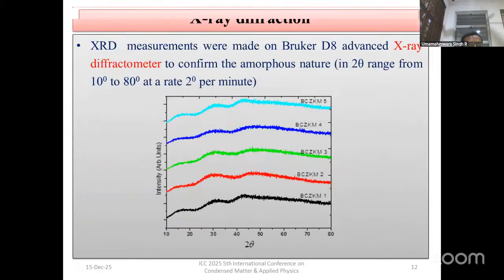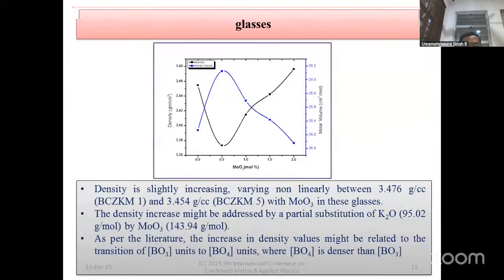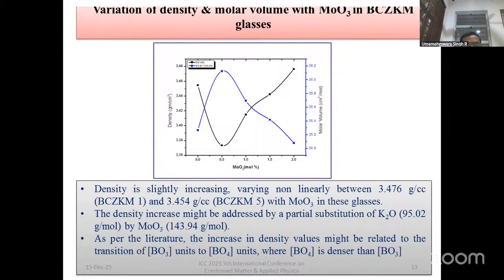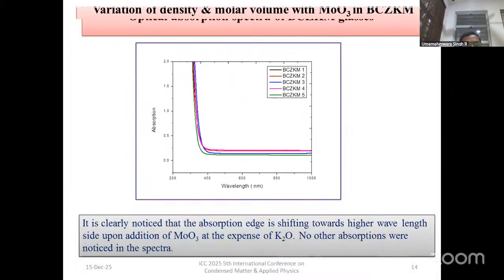These glasses were taken for characterization, starting with XRD, X-ray diffraction, where we found there are no sharp peaks, which indicates that it is a good amorphous material. After that, we studied the density of the glass materials. The density is slightly increasing, and the requirement for radiation shielding applications is that density increases. It increases with non-linearity, from 3.45 to 3.47 grams per cc with the increment of MoO3. We also studied the optical absorption spectra, where absorption was noted, and this indicates the optical properties very clearly.